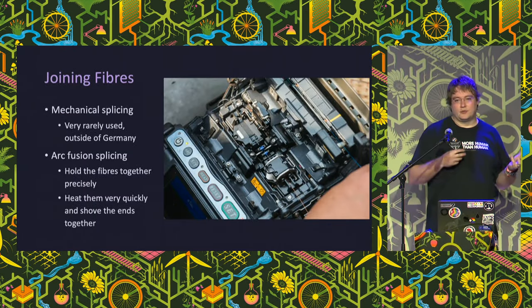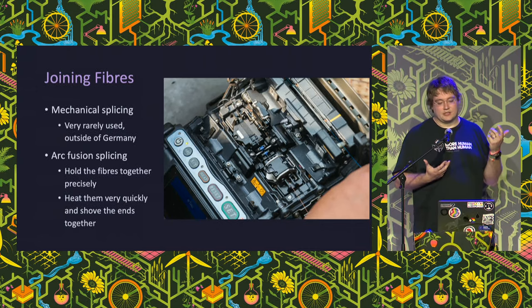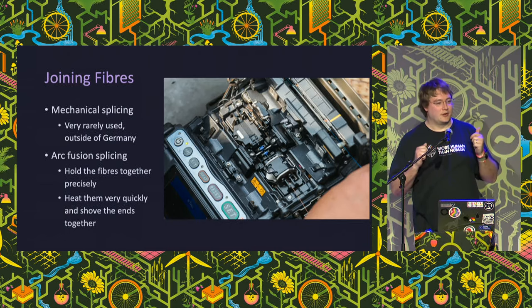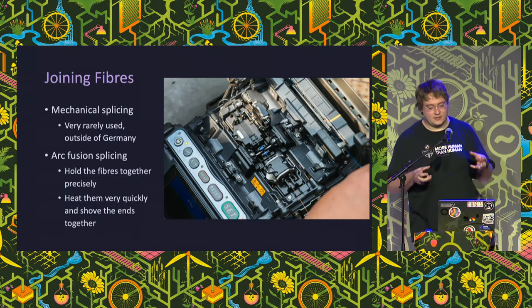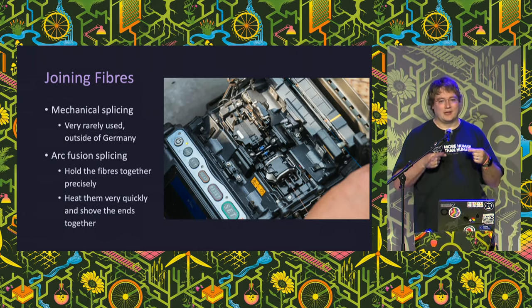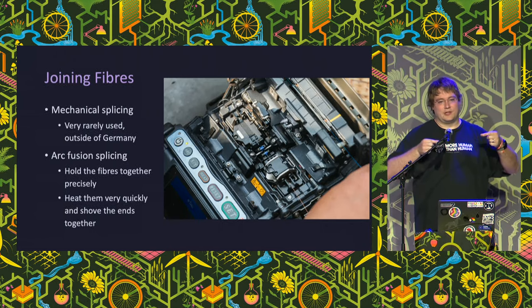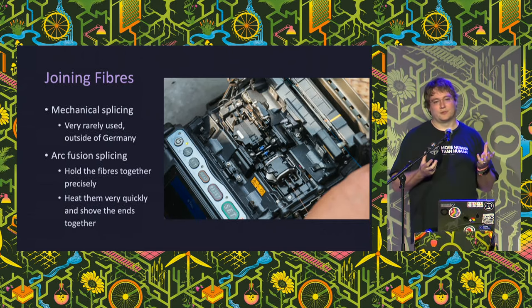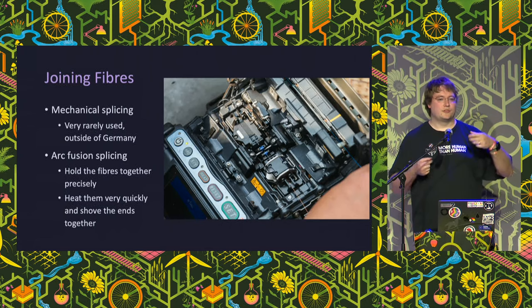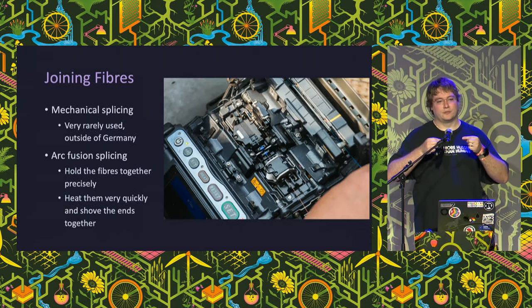To make networks we have to be able to join bits of fiber together. There's mechanical splicing and arc fusion splicing. Mechanical splicing isn't used commonly - the German market has a huge take-up of it but that's the only place I'm aware of. In the rest of the world we use arc fusion splicing, which involves a machine with two XY positioning stages and a microscope. The microscope can see the core, lines the two ends up, and uses an arc to melt the glass and fuse them together - controlled by a little microcontroller. We also typically put heat shrink around the splice to protect it.